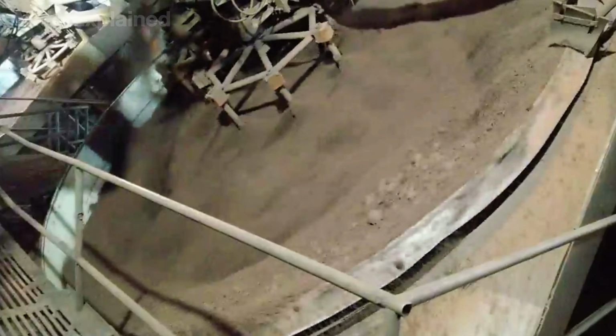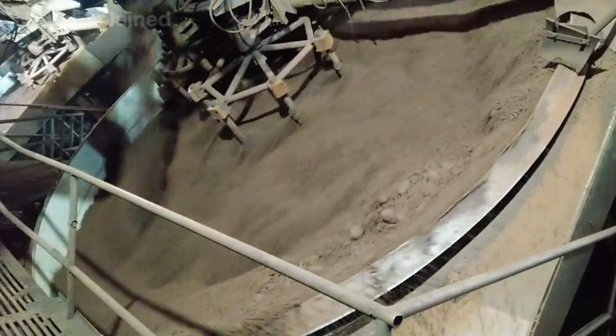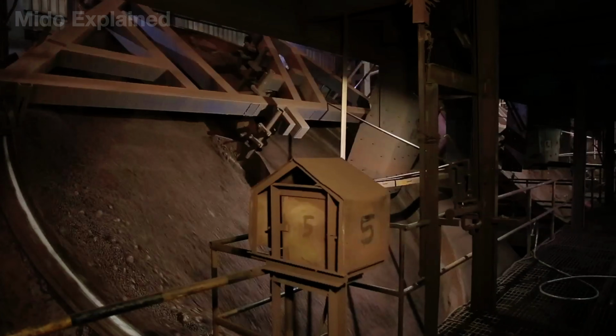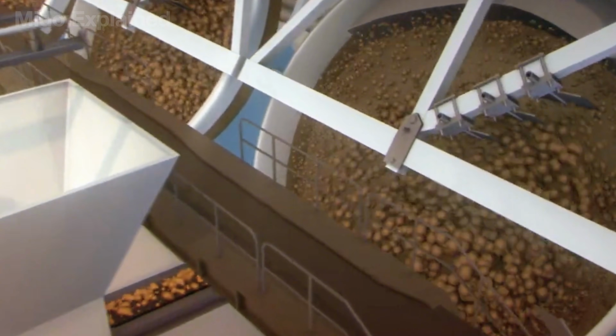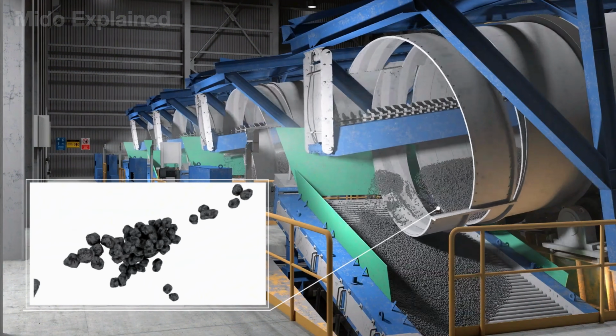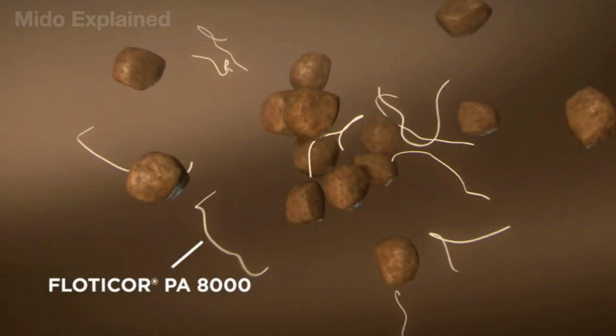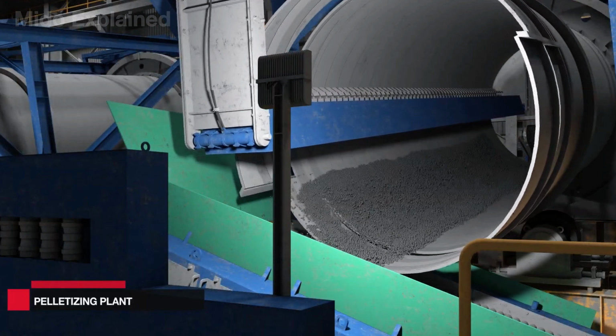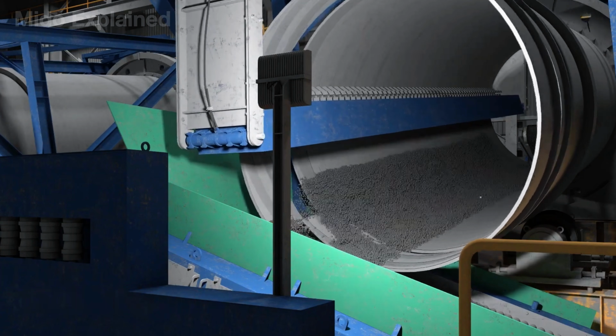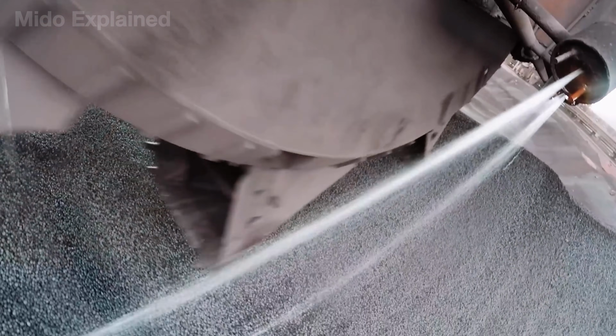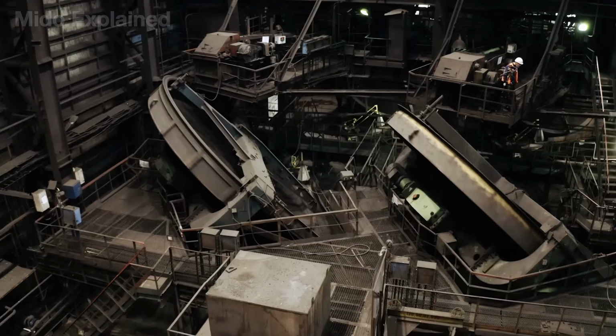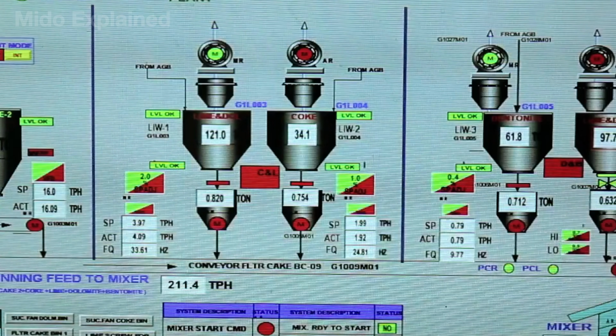In its fine powder form, the particles were too small and easily obstructed the flow of hot air inside the blast furnace. Therefore, the concentrate was mixed with a small amount of bentonite. The mixture was then fed into giant pelletizing discs over 20 feet in diameter. As the discs rotated continuously, the ore particles rolled and clung to each other, forming nearly spherical pellets about 0.5 inches in diameter, roughly the size of a marble. Interestingly, this shape wasn't for ease of transport, but rather to help distribute the hot air evenly during steelmaking, thereby improving the efficiency of the blast furnace.